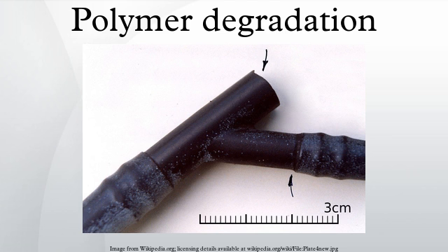The problem of ozone cracking can be prevented by adding anti-ozonants to the rubber before vulcanization. Ozone cracks were commonly seen in automobile tire sidewalls, but are now seen rarely thanks to these additives. On the other hand, the problem does recur in unprotected products such as rubber tubing and seals.